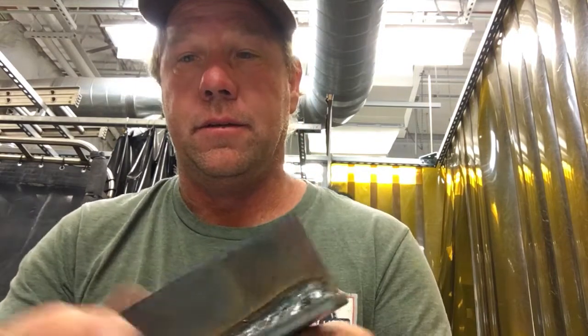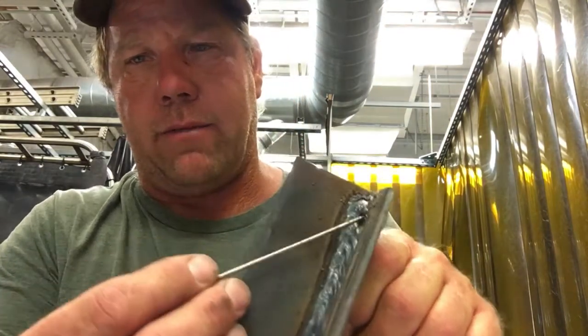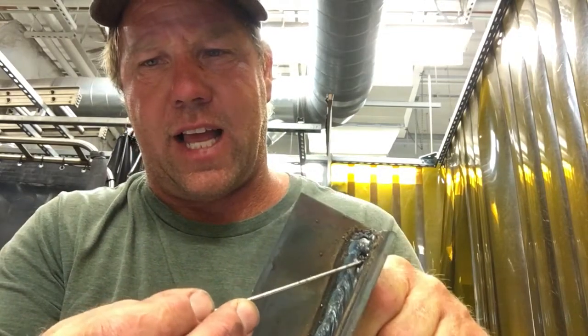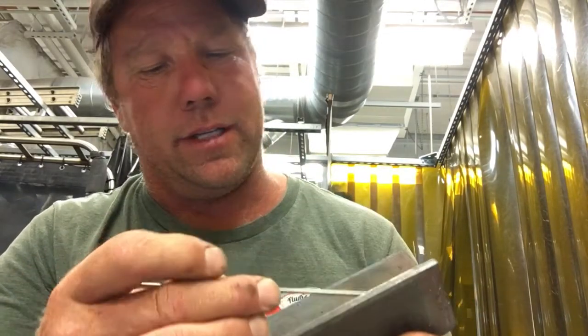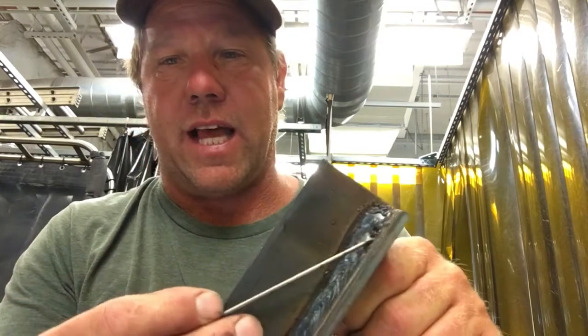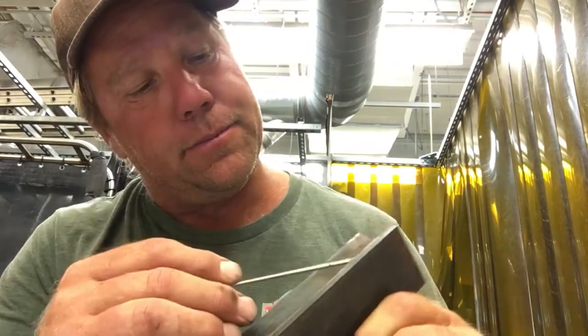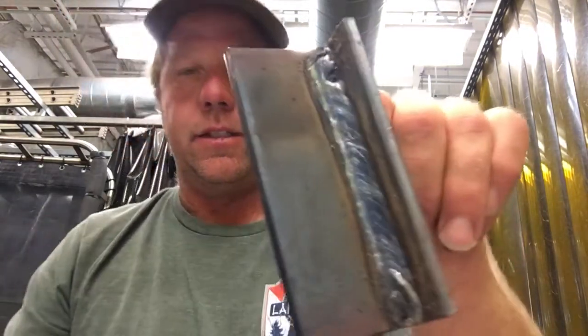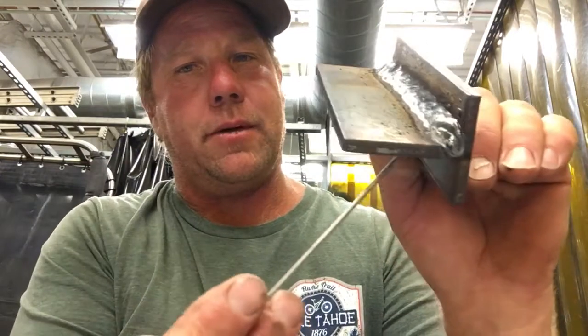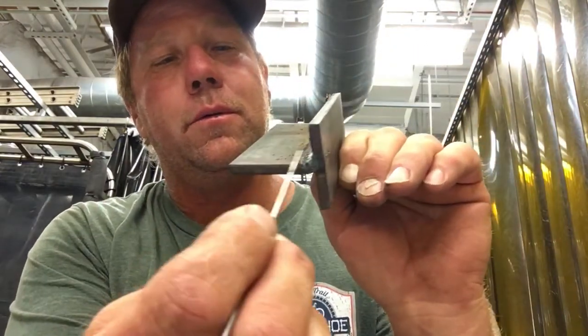So let's just start off with the one that's still together. Nice and simple. This one has some defects too, as you can see. Slag pocket right there. That is a surface of slag that's still slag in there. I could chip it out if I wanted to. There's a bit of slag left on the surface of the weld. Just like so. So that is a slag pocket. Back here at the bottom, we would call that a little bit of arc blow.